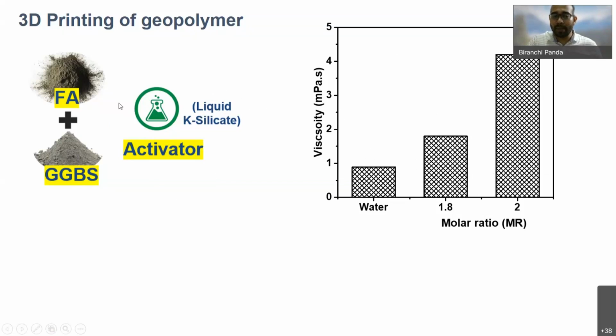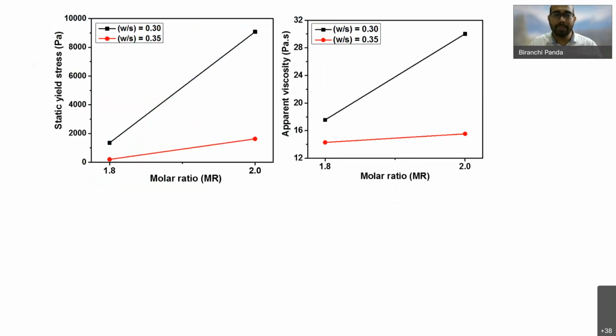So ultimately what is happening here is that according to the viscosity of this activator, we are going to end up with a material which is higher or lower viscosity. And as you know, in concrete printing, we have to carefully control the viscosity of the mix. So it is important again to find the suitable activator for your application. As you can see, different activators and different molar ratios are creating mixes with different yield stress and viscosity, because the activator is playing a critical role in controlling the viscosity of the final mix.